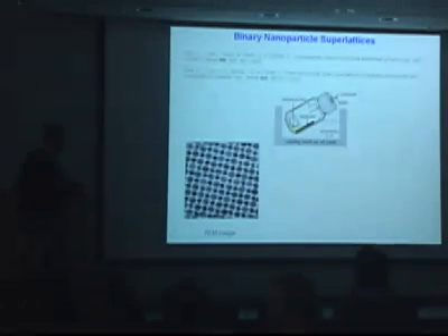But you can make a next step, and that turned out to be even more interesting, where you independently prepare two types of nanoparticles. For example, you cook lead selenide nanocrystals and independently make gold nanoparticles. Mix the two colloidal solutions together and let the solvent evaporate. If you hit the right spot in the parametric space, or just control temperature, pressure, and solvent, then this solution, upon evaporation, will undergo a disorder-to-order phase transition,